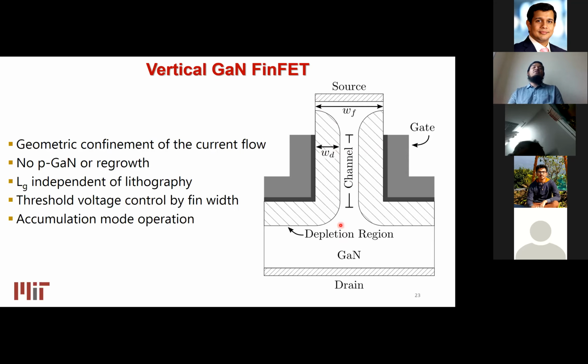And we found from some simple calculations that we can also control the threshold voltage of this device by just adjusting the width of the fin in these devices. This device operates in the accumulation mode of operation, where we apply gate bias and accumulate carriers in the sidewall.